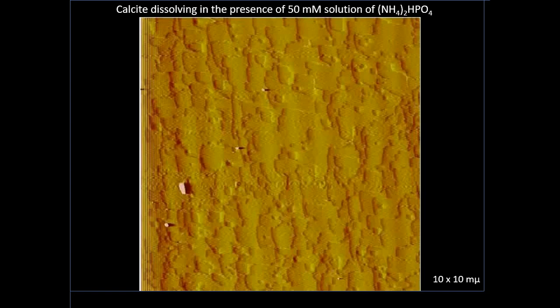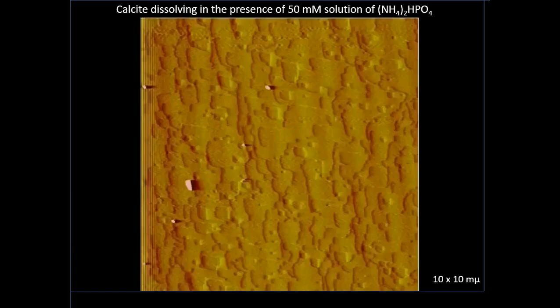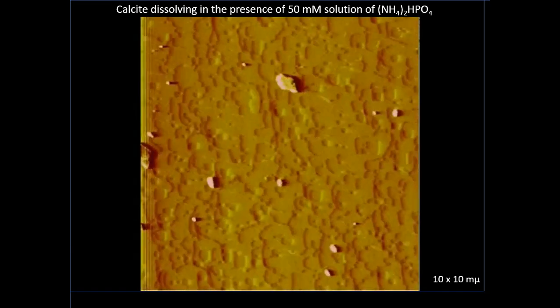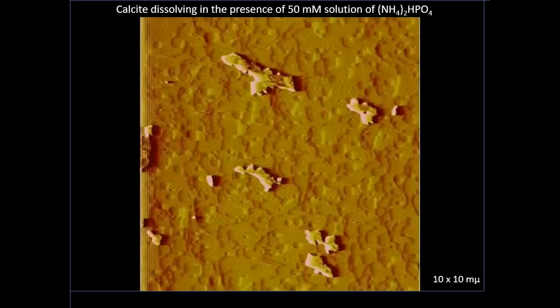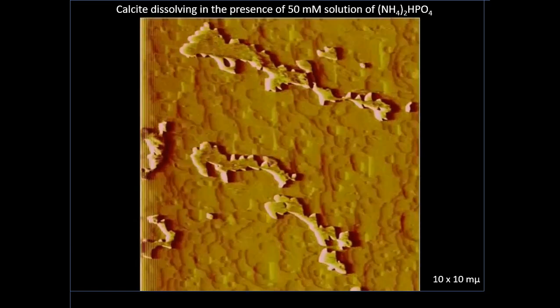Okay, here's another example. We've got calcite dissolving again. This is a bigger section, 10 by 10. I'm adding here a solution of 50 millimole ammonium phosphate. I've also done it with sodium phosphate. But I'm totally undersaturated with respect to any phase. The little rhombohedral edge pits look smaller because it's a bigger area, but the Z direction is still on the nanoscale. You can see some little nanoparticles there, and this should run. Let me do that again. Yeah, here we go. The edge pits are spreading. You can see that there's dissolution, but we're getting nanoparticles formed all over the surface.